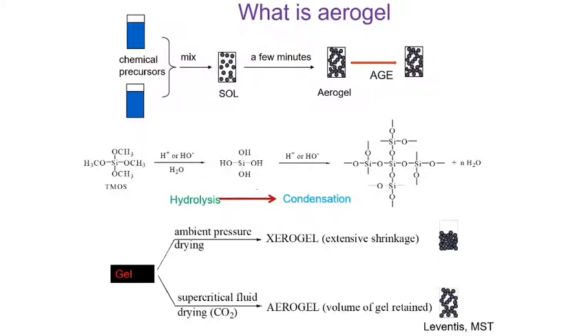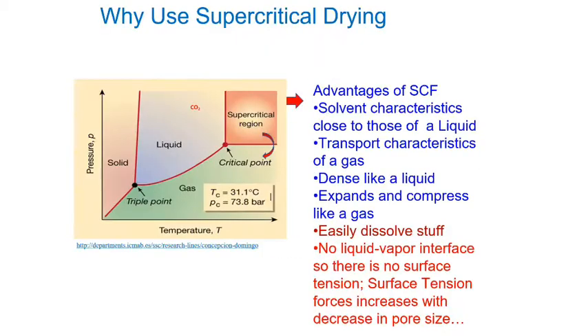And when that happens, if, for example, you use ambient pressure, it's going to shrink too much. But if you use supercritical fluid, then the shrinkage is not as significant as here. So our job is to maintain that network without breaking it. Because when we have this network, now we can add other components. We can add very interesting components to it that will customize it the way we want.